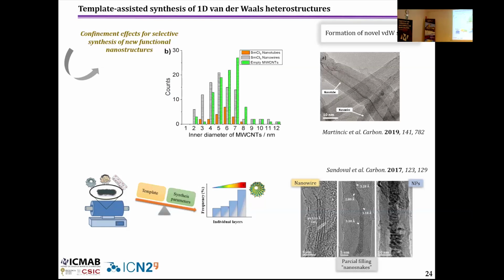That before was like an accident. At the beginning they were trying to prepare nanotubes, then the catalyst they introduced ended up inside, somehow by accident. But there are approaches that can oxidize or reduce the material you put in. So you can use an organic precursor, or a salt to do it. But the problem if you use a metal and you want to decompose it is that you don't fill, but decorate with nanoparticles. So usually the decoration of the external surface is preferred over the filling.